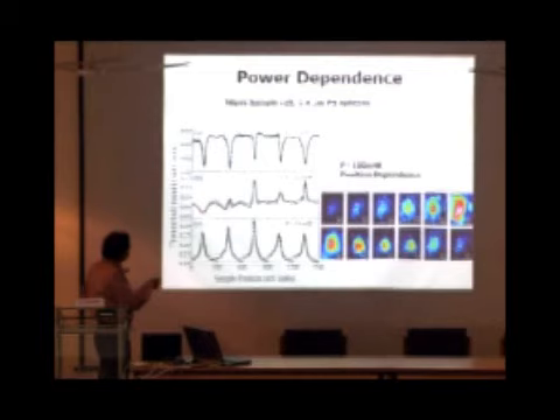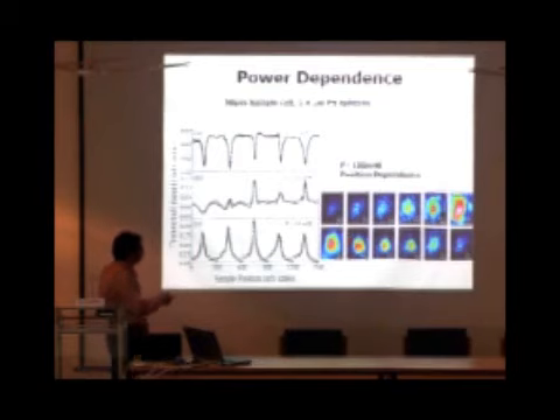But as you increase your intensity, at certain intensity you start seeing this enhancement in transmission. So essentially when you have the close packed structure, you have very nice large transmission.